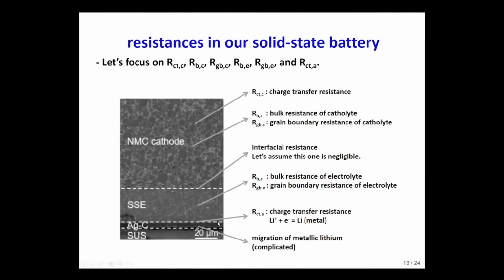Since the lithium ion is going to be reduced at the interface between the solid electrolyte and the silver carbon layer, the movement of metallic lithium through the silver carbon layer should be considered too. But this behavior is quite complicated, so it is not included in the scope of this work.